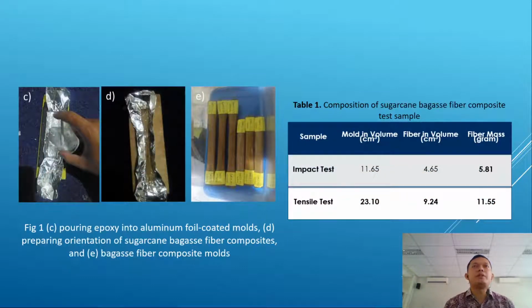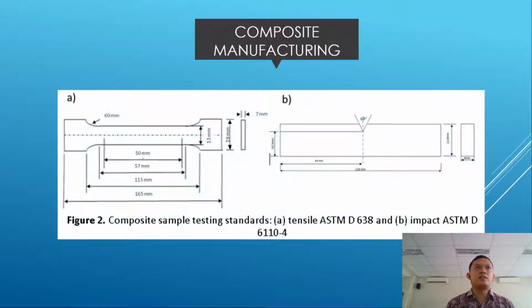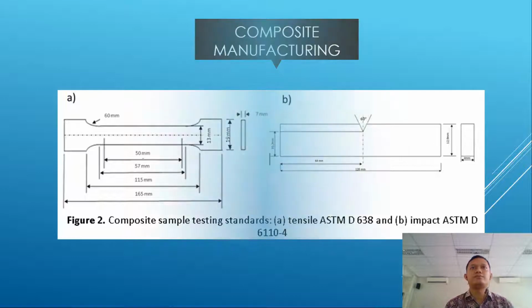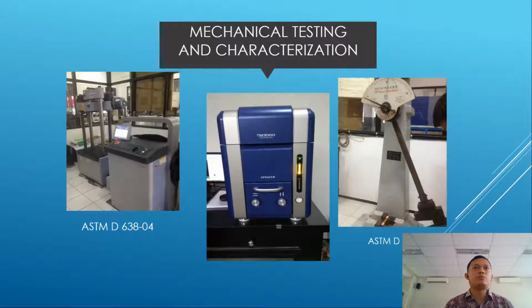And this is about the preparation for testing. We use ASTM standards, and then we pour into the mold to make the impact test and tensile test. This is the mold volume, fiber volume, and fiber mass. The composite manufacturing, as I said before, is according to ASTM D638 for the tensile, and ASTM D6110 for the impact. We also use mechanical tests, and SEM characterization to observe the fiber surface interface, and we analyze the fracture patterns.